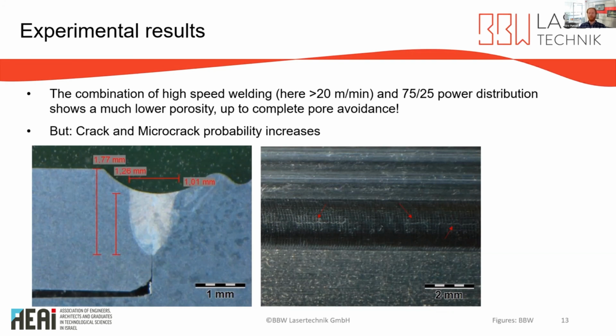pore formation. We did different cross sections. Unfortunately, I have for this presentation no longitudinal cross sections. But as already mentioned in the beginning, we could come into another process window with a higher probability for hot cracks for some aluminum alloys, which is exactly the example in this case. So for an understanding, we have milled down the surface near the weld seam, and we can see here in the weld seam small micro cracks. Therefore, process development is very often a balancing act, finding the right process window.